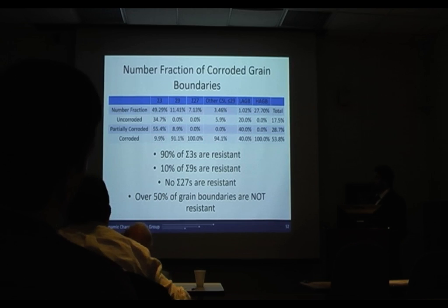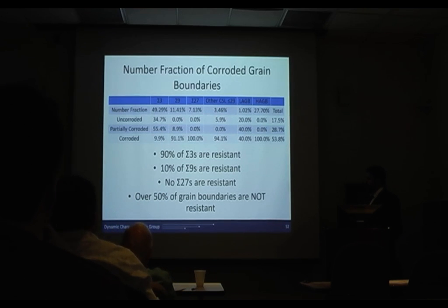What we found was that 90% of the sigma 3s were at least somewhat resistant, but less than 10% of the sigma 9s were. And no sigma 27 in this case resisted corrosion. Also, when we look at the total number fractions, over 50% of the grain boundaries do not resist corrosion at all.